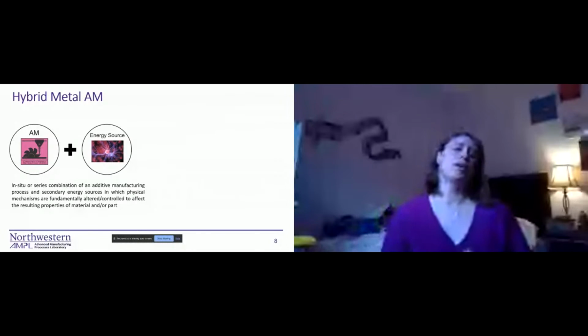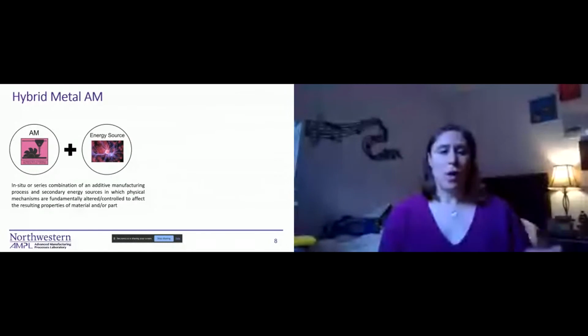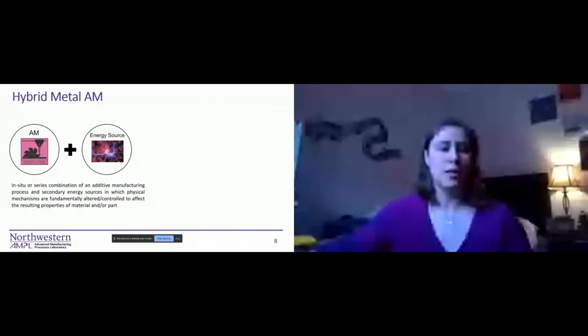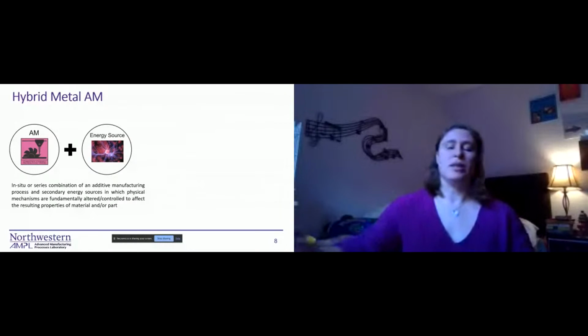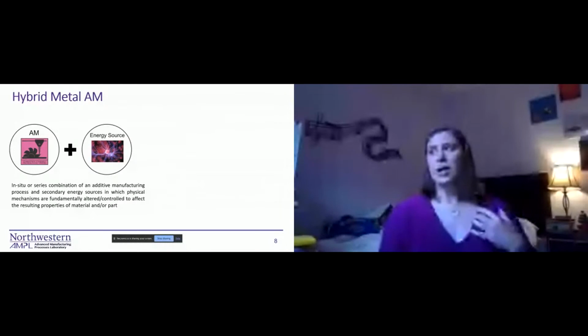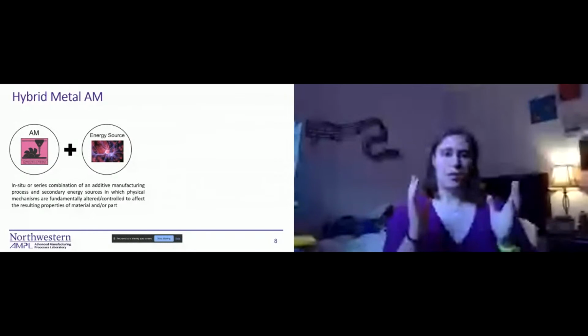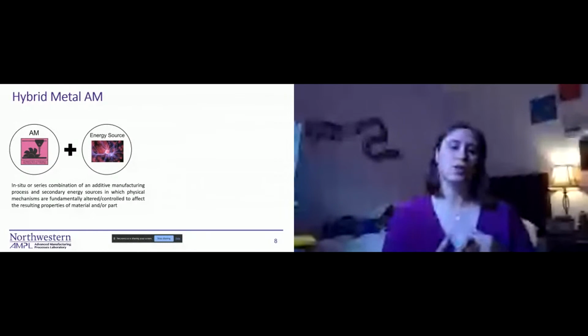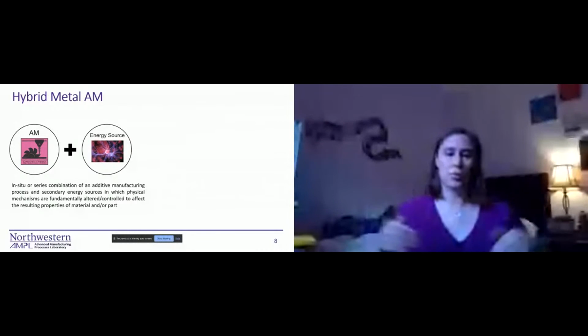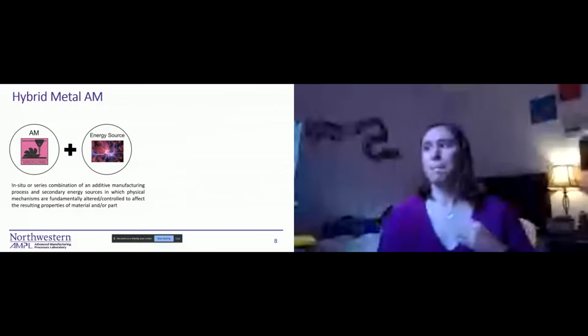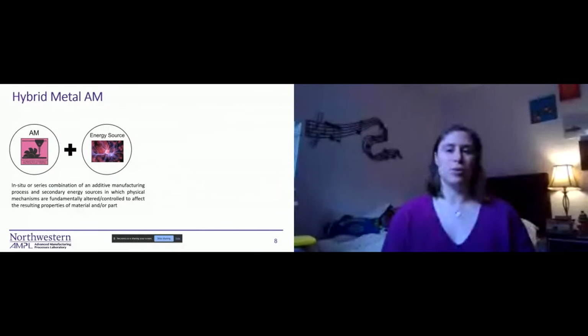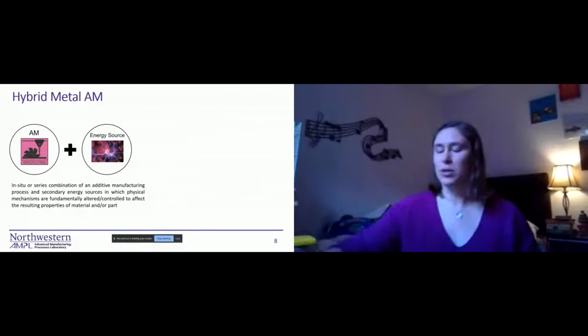So an example of this is using wire arc additive manufacturing with a second. Here we see the WAAM process with a laser beam that is included within the melt pool. An oscillating laser beam was used, and the changes in the melt pool flow pattern actually allowed the release of pores from the melt pool up to the surface. So this is just one example. I'll be going over a couple of different ones later in the presentation.